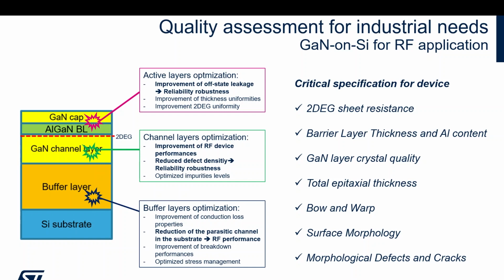So again, you have to control the conditions, you have to control the stoichiometric composition. See how complex it is, especially on silicon. On silicon, you have a buffer layer to reduce the stress.